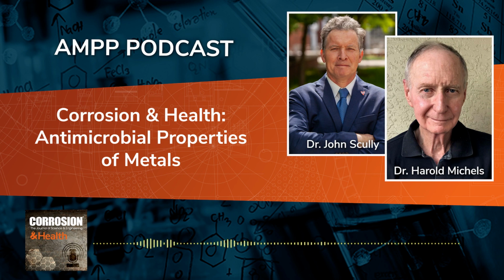You might say, why does the copper oxide work? Because the corrosion step has already taken place. Like if you embed something like the copper oxide. So you will see in some applications, people have used these copper oxides, and there, it's not in the corrosion, you've got to have an anode, cathode, and you've got to have an electrical and ionic path between the anode and the cathode. But when you have the oxide, you've already created the cupric and cuprous ions.